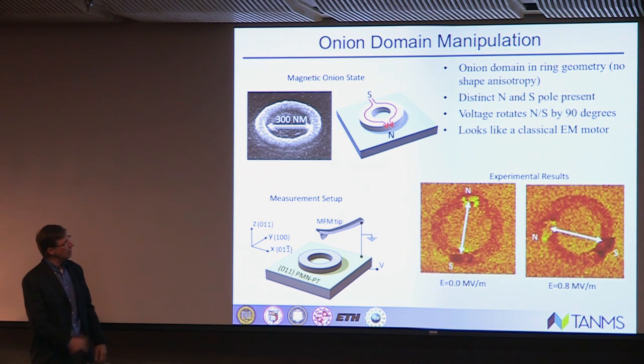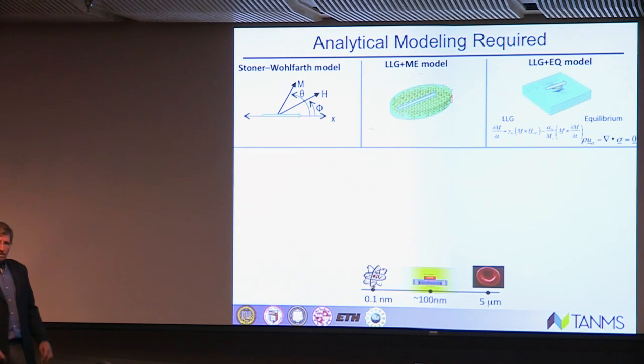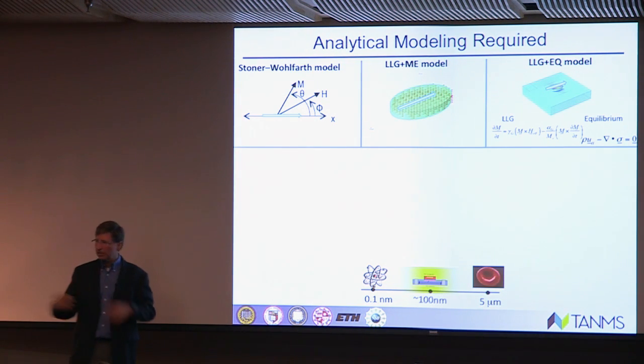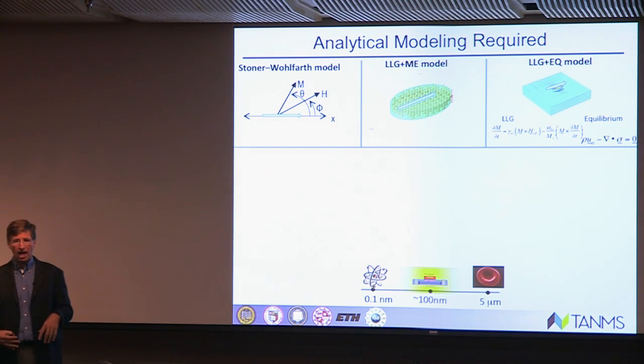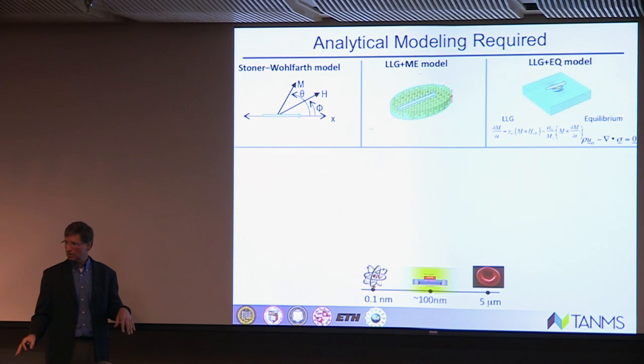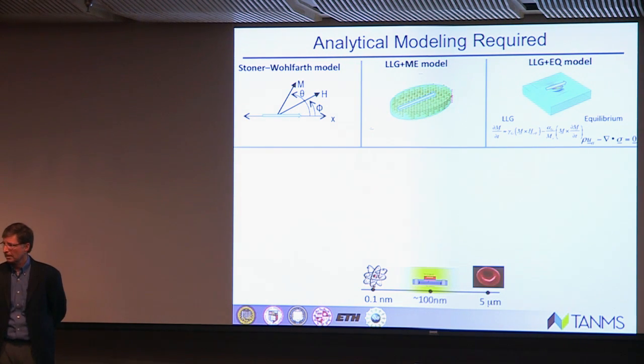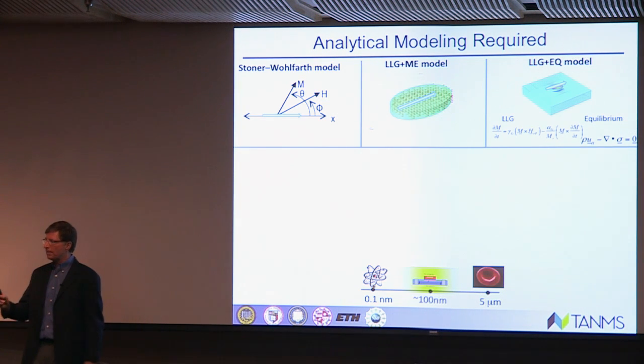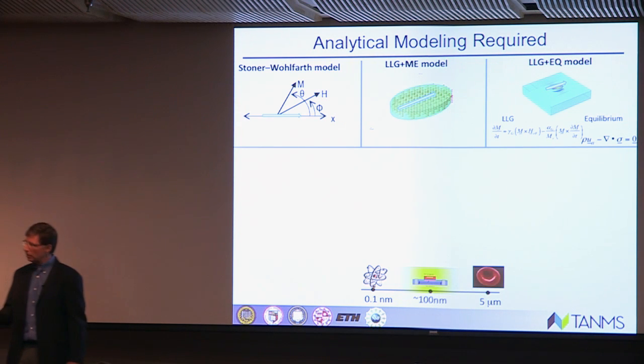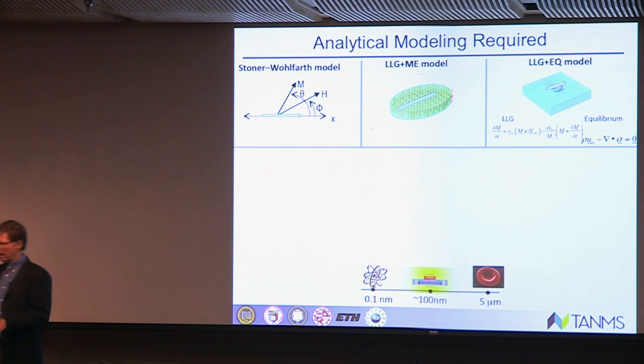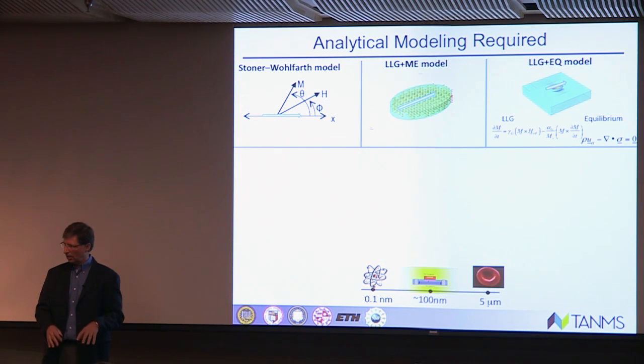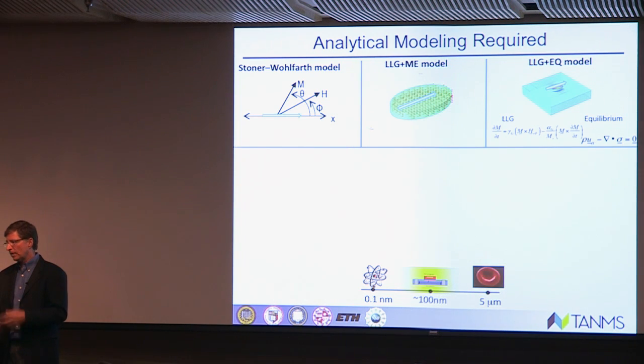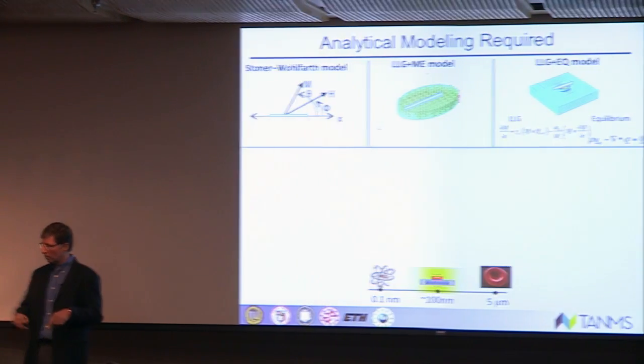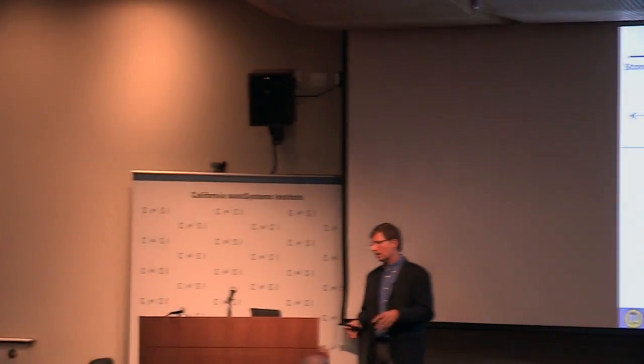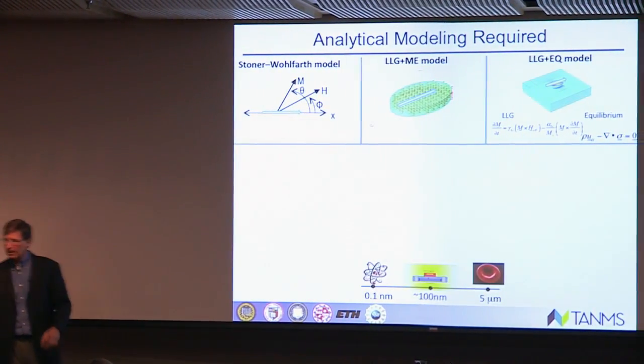So this looks like some interesting stuff here, but let's go smaller than this. As we tried to go smaller, we started finding out we can't just go through this make it and test it philosophy. We have to rely on analytical models. So I'm going to spend one slide just on analytical models real quick. What about domains within the rings? Right now, the domain walls depend on what size ring you actually fabricate. So you can fabricate a ring without any domain walls, depending on the properties of your material and the size of your ring. You'll get to a size that you have domain walls, and you'll get to a size that you actually start forming vortex structures. Typically, we're focusing on ring structures below about 3 to 5 microns. So now we started coming up that we really had to start looking at analytical models.